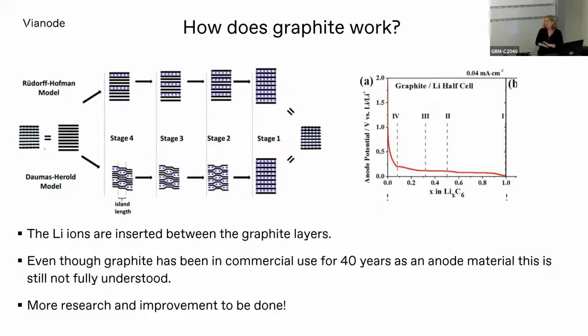But what we see that is exciting about graphite is that even though it seems like a very simple system, where you have layers of carbon atoms all in the same structure, seems very simple. And yet it has been the commercial anode material of choice for 40 years. And we still do research on it. And we still don't entirely understand the mechanisms for storage of lithium inside the material. In fact, we have graduate students at University of Oslo now doing in situ XRD analysis for us on how you charge and discharge graphite materials to look at these different models that you see here of how the lithium ions preferentially fill into the different layers. Because they don't just fill one next to another all crowded into one space. You tend to fill either the furthest apart in different layers or maybe in different sections of the layers.